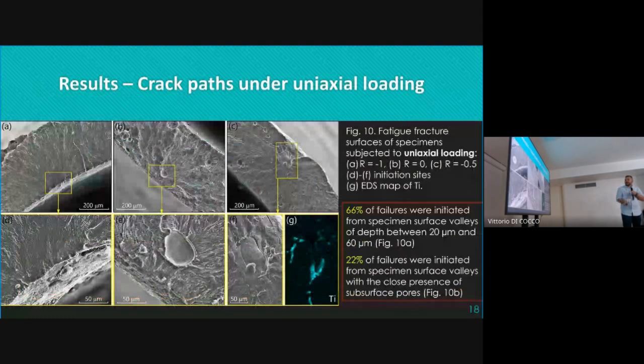Crack paths under uniaxial loading. Like I said before, there was porosity, obviously, but in most cases the crack initiates from the valleys, and for 66% of those initiated cracks, there were no pores within approximately close distance from the place where it initiated. For 22%, there was a pore very close to the valley, but we couldn't find any impact on the actual fatigue life for those specimens. So probably it was just a coincidence, but the pores were not so important.